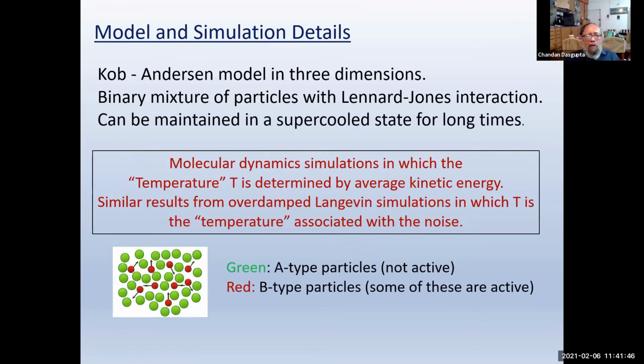I will not go into the details. It's just basically a few things that you need to know. This is a binary mixture. It's not a single component system, so that it can be maintained in a supercooled liquid state for a long time. Otherwise, the liquid basically crystallizes. Interactions are the usual Lennard-Jones interactions. And I'm not going to tell you exactly what the epsilon and sigma parameters are, but they're chosen in such a way that earlier simulations have shown that this system can be maintained in a supercooled state for a long time, so that one can study the dynamics in that state.